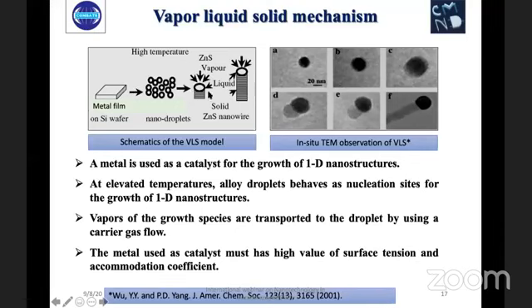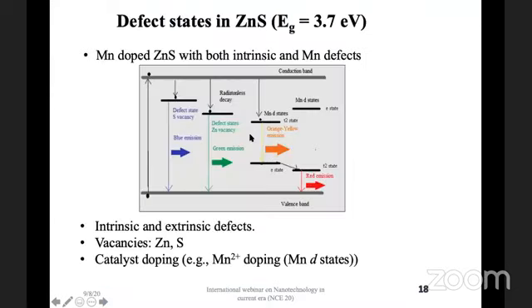The vapors come onto the surface, they supersaturate the surface, and then they condense at the interface of this particle and the substrate, and they start growing into a wire-like structure, and we get a straight wire. This was demonstrated long ago by Professor Wu. They took real-time TEM images to show the growth of silicon nanowires. But nevertheless, the phenomenon is the same for all those which employ the vapor, liquid, solid, VLS technique.